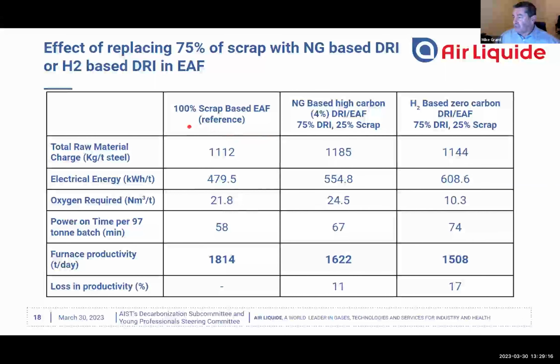If we replace 75% of that scrap with DRI, and a high carbon DRI, which is desirable, we can maintain our chemical energy by adding a little bit more oxygen, but our power consumption goes up considerably, by about 70 kilowatt hours per ton. And this reduces the productivity of the furnace by about 11%. So this is one of the drawbacks of DRI, but you'll be reducing your CO2 emissions.